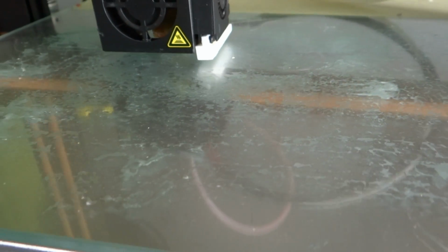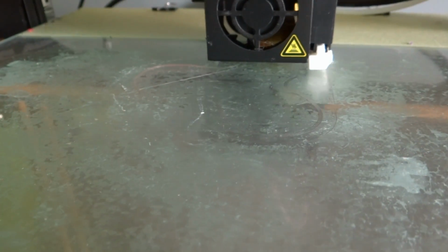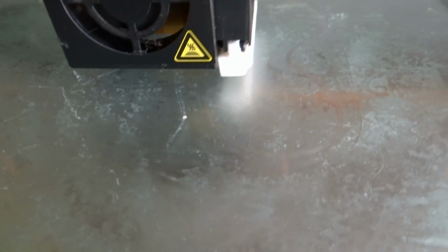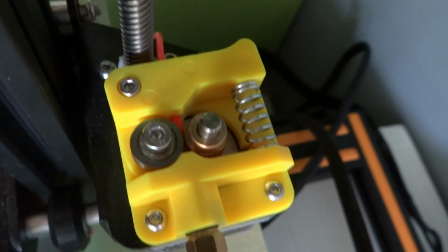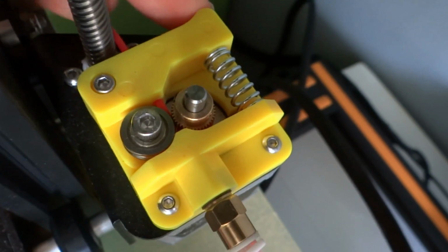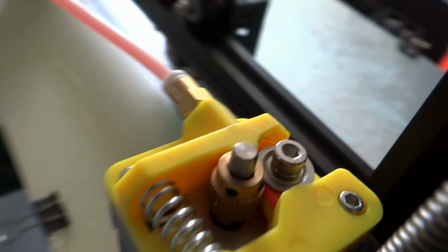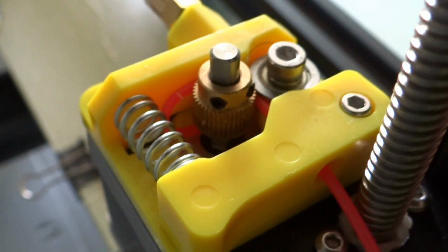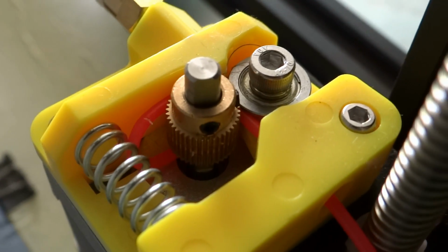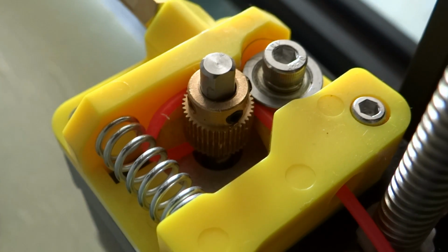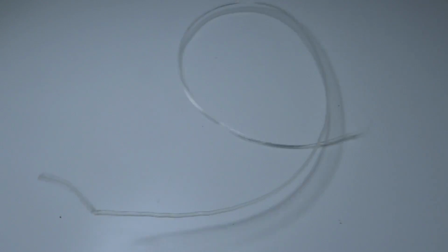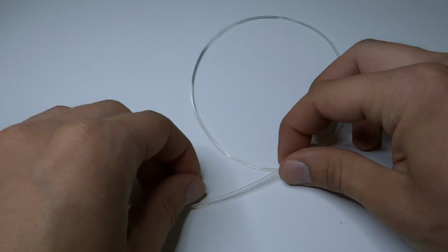So let's start printing. Settings same as for PLA. Head temperature 225 degrees Celsius. And then filament has jumped in the extruder. Same thing during the second try. Reason? Too flexible filament. So let's try with different one.